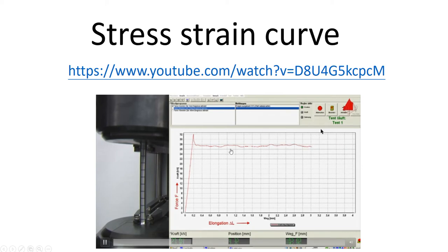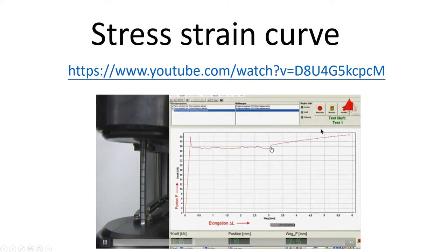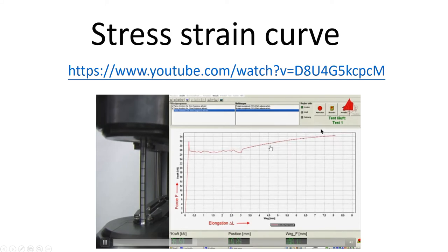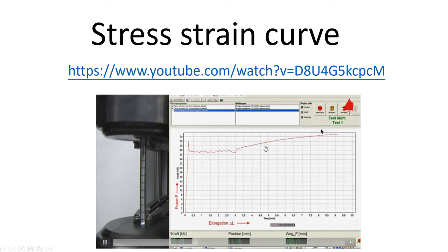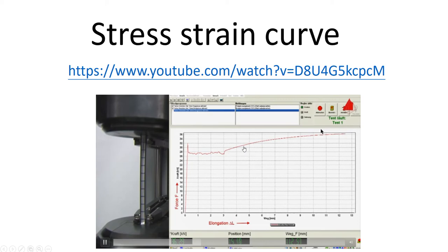After a certain strain, known as the Luders strain, the force increases again. The material opposes an increasing force against the imposed elongation. It strain hardens. Up to the point of maximum force, the test piece is strained uniformly along its length. This means that the test piece gets longer and thinner, but keeps a cylindrical shape.